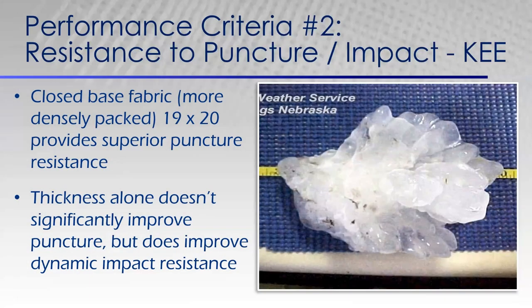When we look at KEE, KEE has that closed fabric package, 18 or 19 by 20 stitches per inch. That densely packaged fabric provides superior puncture resistance of the product. So while your thickness, again, has very little impact on your puncture resistance, it does help with impact resistance, but due to the nature of the densely packaged fabric package of KEE, it is extremely puncture resistant. Here's another hailstone on a KEE roof.